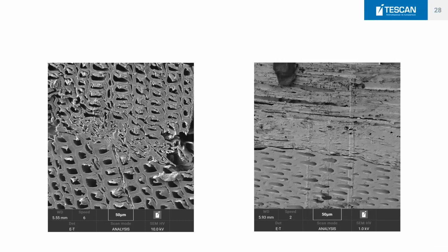Or you could see how the interaction between the particles was on the left-hand side, but that they were not really crushed and compacted. And you can observe on the right-hand side that this was not really true for the alternative particle board, where the compaction was significantly higher.